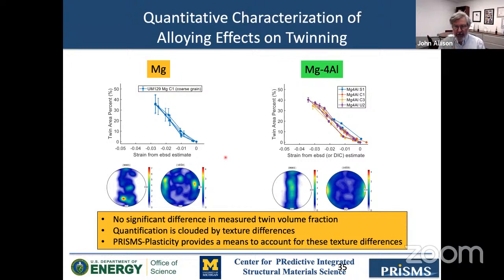And the literature on this is kind of spotty. Some theorists proposed that there are no effects. Some have even theorized that alloying can lead to reduced twinning strains. So this is an important issue for us. However, quantifying this is clouded by differences in texture that are natural. So PRISMS-Plasticity provides us a means to account for these texture differences.